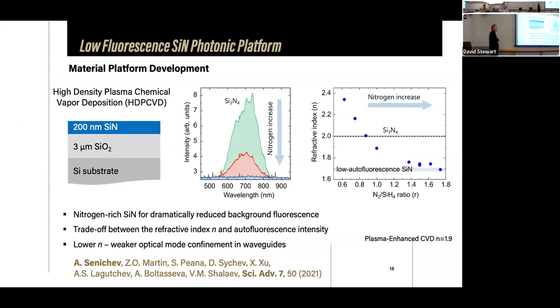So what are the tricks? The first trick is why people didn't see single photon sources. It's because of the fluorescence background. If you do nothing, if you make this stoichiometric silicon nitride, then basically you have quite significant fluorescent background. And because of this background, you cannot see any single photon sources. And it turns out if you do nitrogen enriched silicon nitride, then this background decreases by orders of magnitude, truly dramatic. So it basically disappears. And that enables us to see really small signals such as single photon sources.